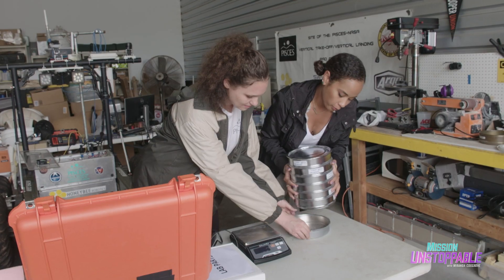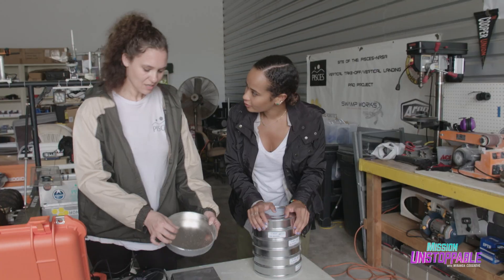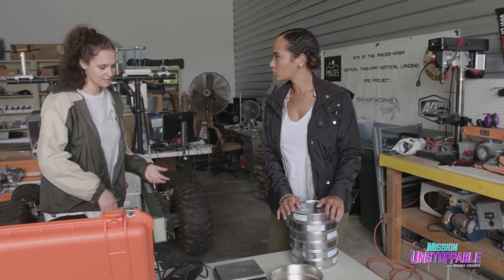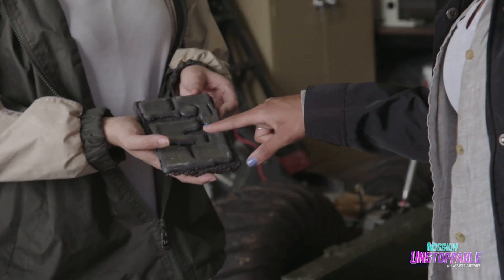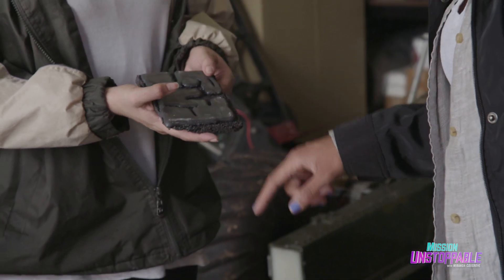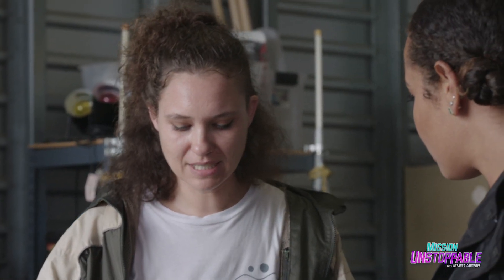After about a minute of sifting, the final result is the consistency of flour. Grain size is important because when we put this stuff into the kiln, the particles are basically free-floating. To make them bond, they want to bond with similar-sized particles. Otherwise they don't sinter or fuse as well — the fine-grained actually slides around on top of the coarse grain with no bonding. When you match the grain size, it typically comes out smooth like this.